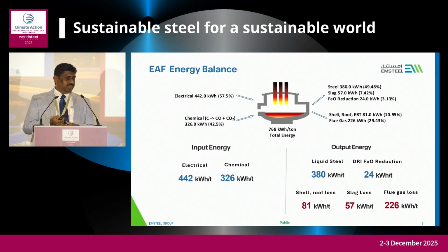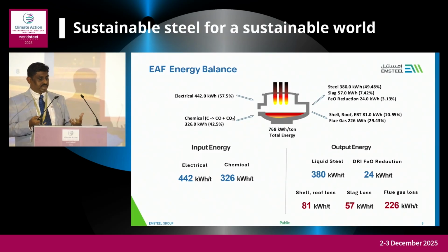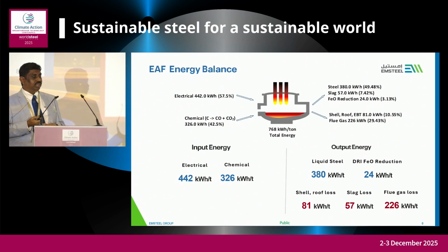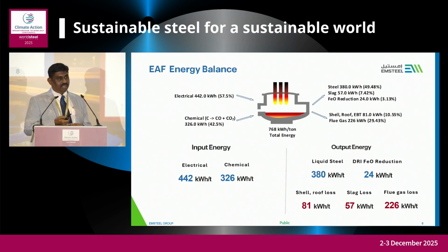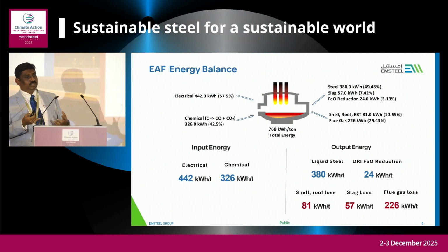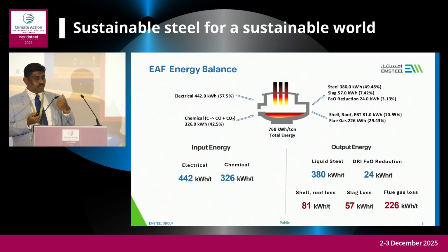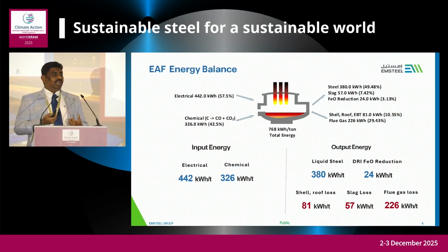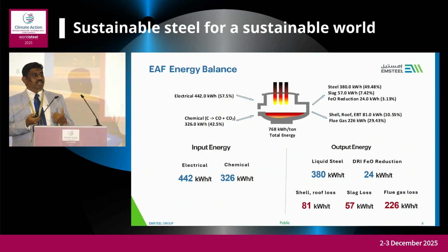If you see the energy losses, here we need to work. Because in the flue gas, we are losing around 226 kilowatt hours per ton. And in the slag also, we are losing 57 kilowatt hours per ton, which is a huge loss. So we need to spend some research to implement waste heat recovery, and energy capture from the slag, to reduce the overall energy consumption.